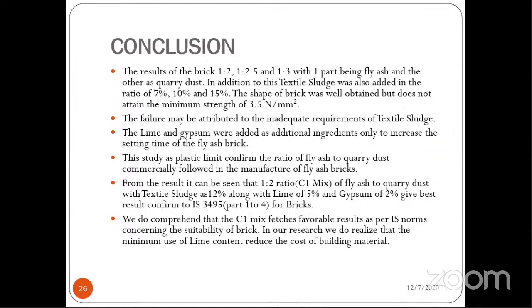The lime and gypsum were added as additional ingredients only to increase the setting time of the fly ash brick. The study on plastic limit confirmed the ratio of fly ash to quarry dust commercially followed in the manufacture of fly ash bricks. From the results, it can be seen that the 1:2 ratio, that is C1 mix of fly ash to quarry dust with textile sludge 12%, along with lime of 5% and gypsum 2%, gives the best result conforming to IS 3495 for bricks.